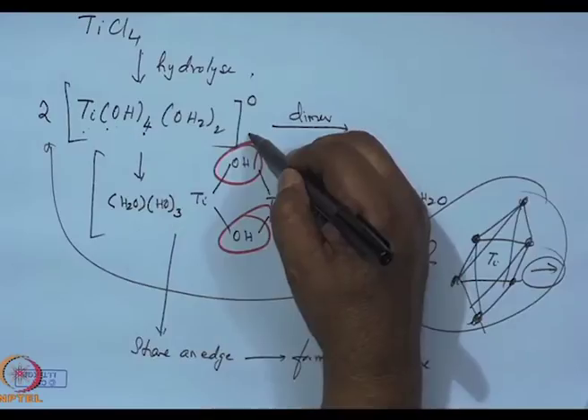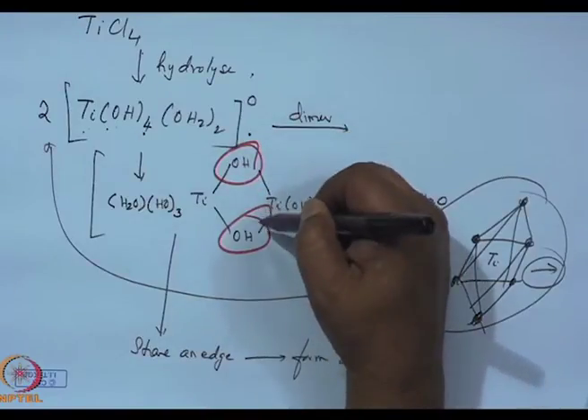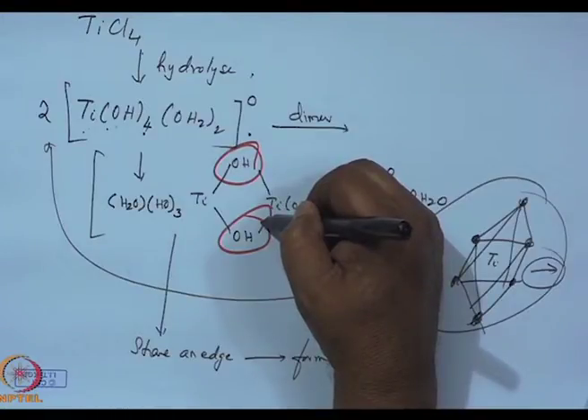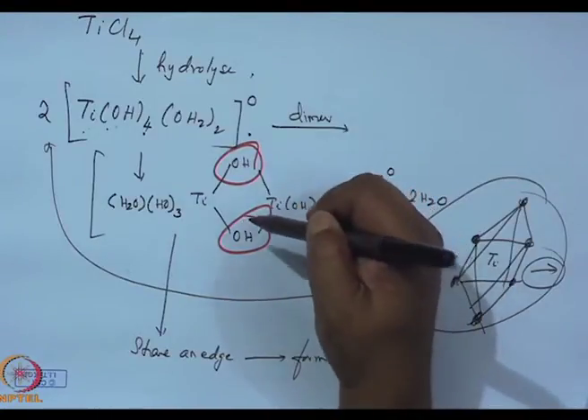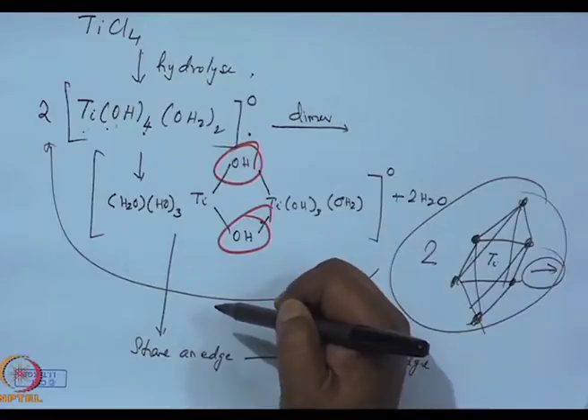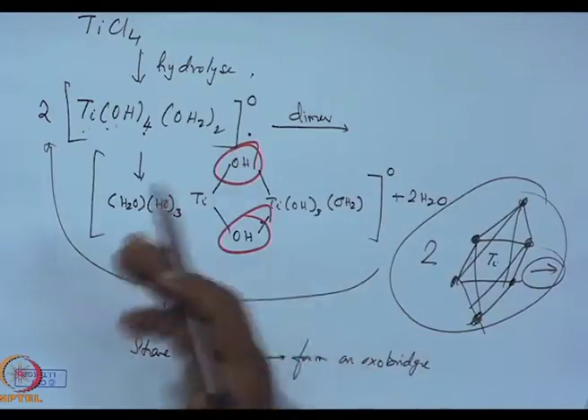So, the anatase one will form smaller chains than the rutile, and hence anatase will be more stable than rutile while self-assembly. So, if we take titanium tetrachloride and use it for self-assembled monolayer formation, what we will get always is an anatase layer on the substrate if we follow the procedure correctly. And the way to do it is to hydrolyze it, form the zero charge substrate, let them combine to give the oxolation. These oxolation products deposit on the surface, they grow by Ostwald ripening, and finally they cover the entire surface.